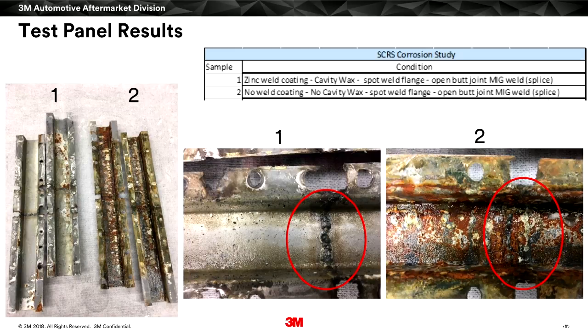So no protection basically on the one in that right slide, number two. And you can see the distinct difference in the corrosion. I mean, that butt weld joint is really going to be in trouble if we start to leave it in there any longer than 500. And this is 500 hours, not 1,500. So you can see how much Mother Nature takes after the part when it's not protected. That's right. And if that was a structural frame rail that the vehicle's relying on to collapse and absorb energy, if it's badly corroded, it's not going to do the same thing.